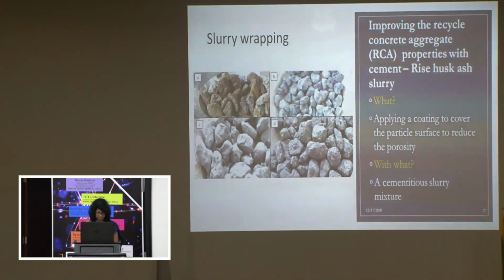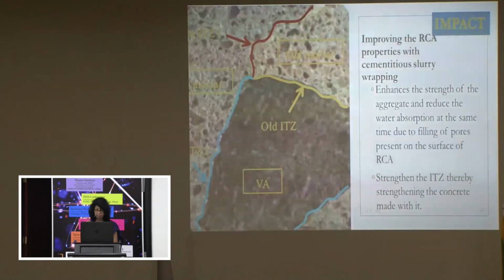We studied the effectiveness of varying proportions of rice husk ash cement slurry as a microfiller to improve the surface properties of recycled aggregates, enabling the reduction of high water absorption. Micromorphology studies done on recycled aggregates improved with carbonation and surface treatment methods have shown that carbonation significantly improves the mechanical properties and the dry shrinkage resistance of the recycled concrete. Further, the slurry wrapping technique used has greatly enhanced the aggregate properties as well.